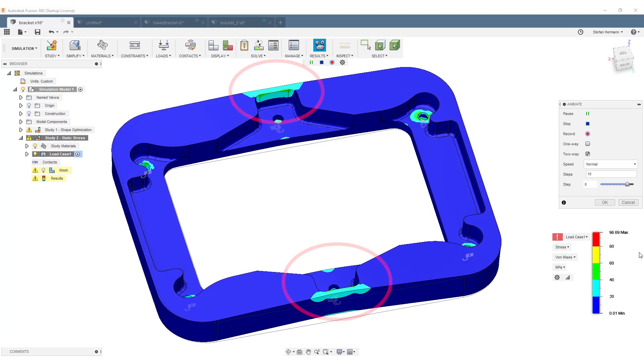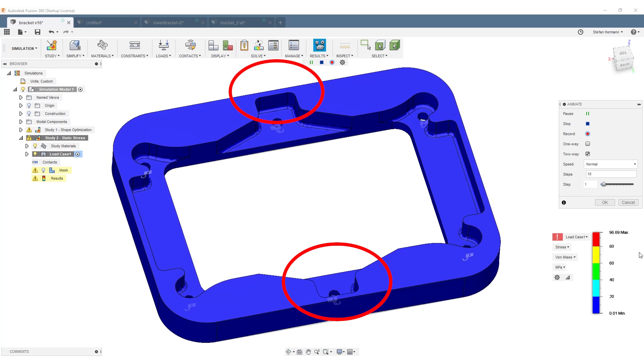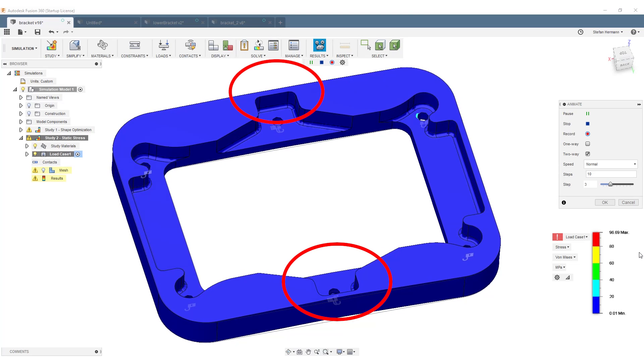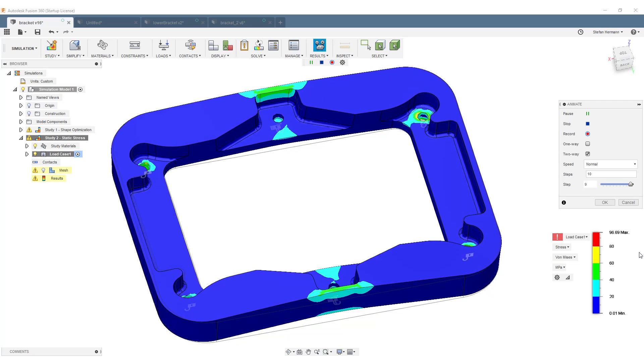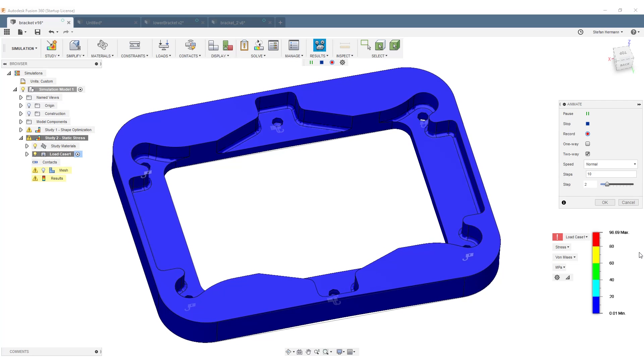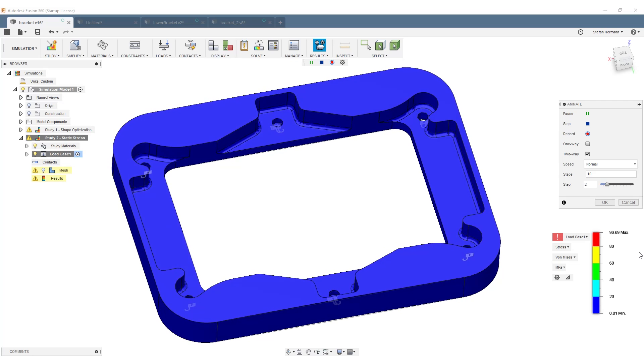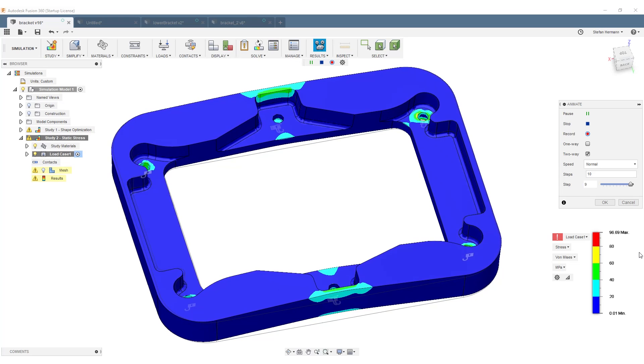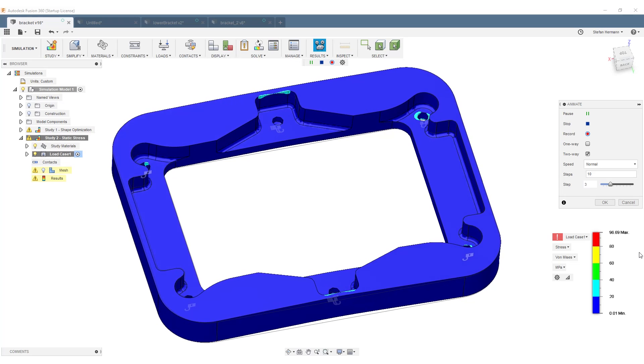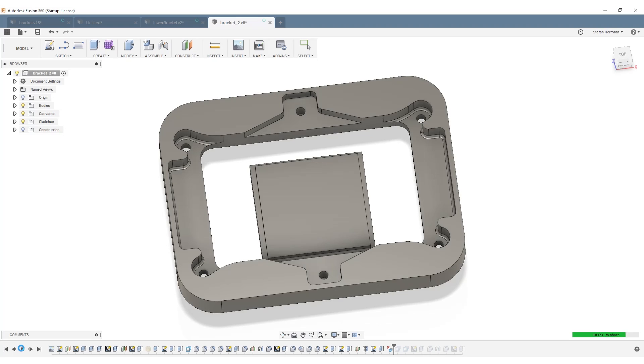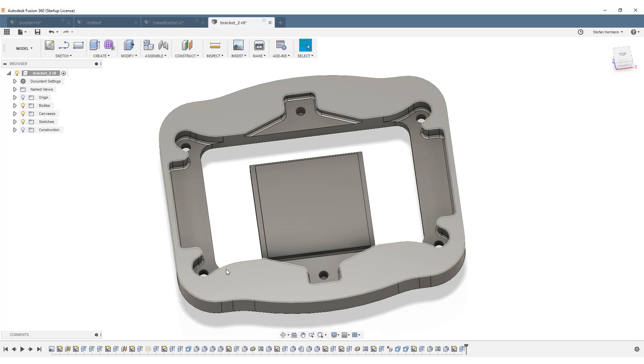So you remember the small lip, we had the highest loaded section? Well, even though the carbon fiber reinforced nylon is really strong and we didn't load it all the way to its yield point, the stresses were just too high. So I simply reinforced that location, covering up some of the cavities below, but I made sure that there was still some clearance.